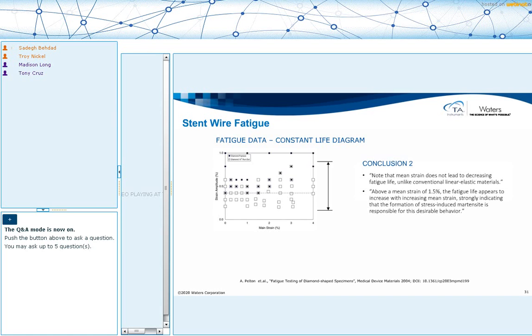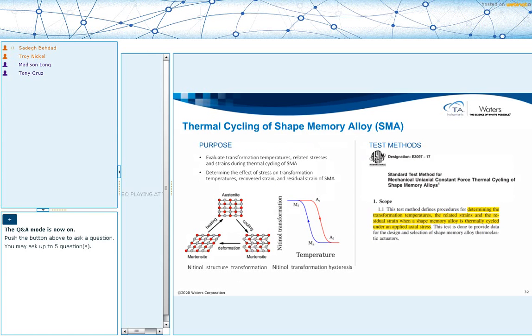And the article says that what they think is the source of this behavior is that the shape memory alloy can have a solid state phase transformation between the two phases that are called austenite and martensite. And the martensitic phase has a better fatigue endurance. And they think that when you apply that mean strain to a higher level, you are inducing a phase transformation to the martensitic phase, and that is why it survives longer. So that is a good prelude to the second example that I'm going to present.